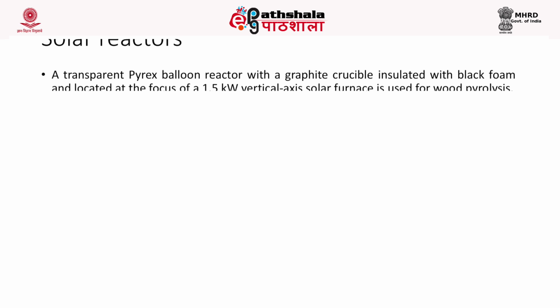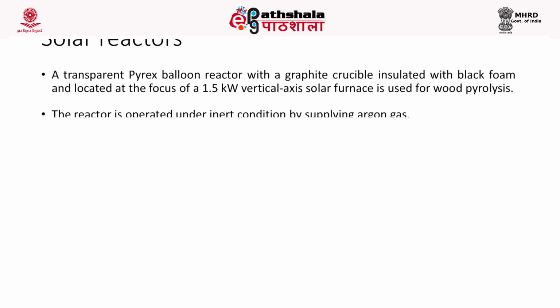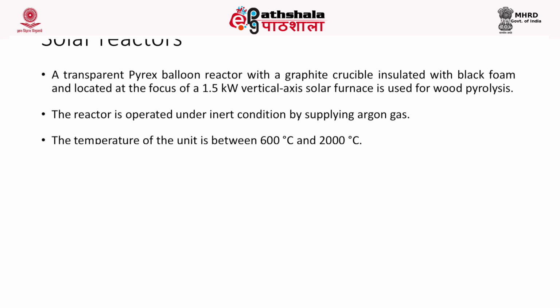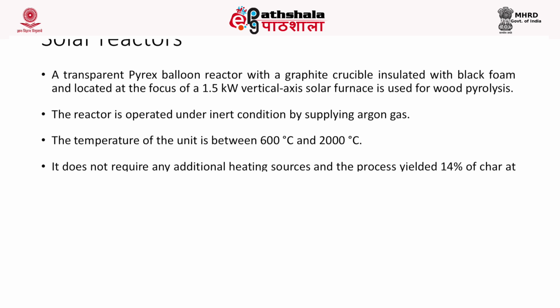The last type of reactor is the solar reactor, where you have a transparent Pyrex balloon reactor with a graphite crucible insulated with black foam, located at the focus of a 1.5 kilowatt vertical axis solar furnace. It is generally used for wood pyrolysis and is operated in inert condition by supplying argon gas. The temperature ranges from 600 degrees Celsius to 2000 degrees Celsius. It does not require any additional heating source and yields around 14% of char at 600 degrees Celsius with a heating rate of 50 degrees Celsius per second.